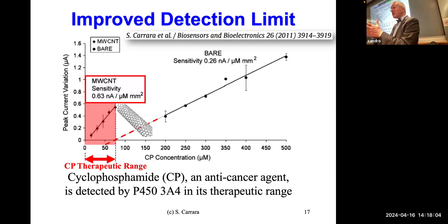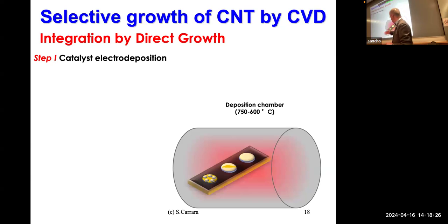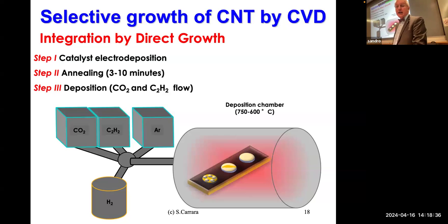So you see, the integration of a nanomaterial brings us back in business in using this kind of enzymatic amperometric sensor. How can we integrate carbon nanotubes? We have many different options. I will present just one, to keep it shorter today. We can, for example, define our multi-panel platform, transfer by electrochemical deposition the precursor film, and then typically flux carbon-based gases to grow nanostructures on top.